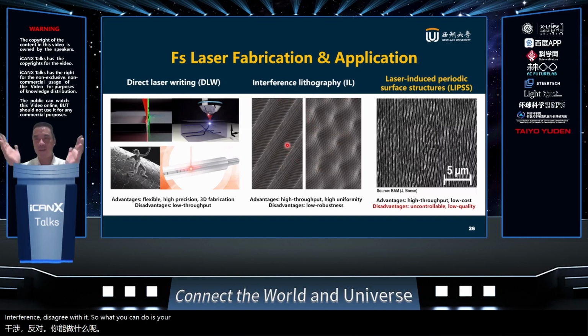So what you can do is put 2 beams together, or 3 beams, or even more beams, and then you can make very uniform, high throughput grating devices or structures. But robustness is an issue, of course. Another problem is that it's not so easy to write very large structures. There's also another interesting thing called laser-induced periodic surface structures, LIPSS. Here the incoming laser light interacts with the surface wave generated at the surface of materials. When they interfere with each other, it's possible to have periodic structures come out of it. So it's very high throughput and low cost, but the disadvantage is very obvious. It's not so easy to control, as you can see from here.